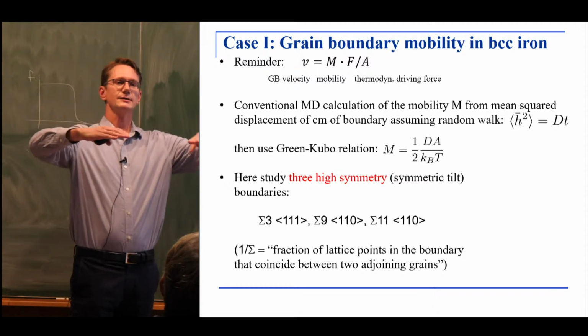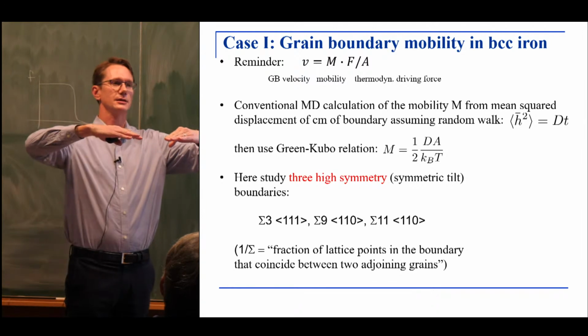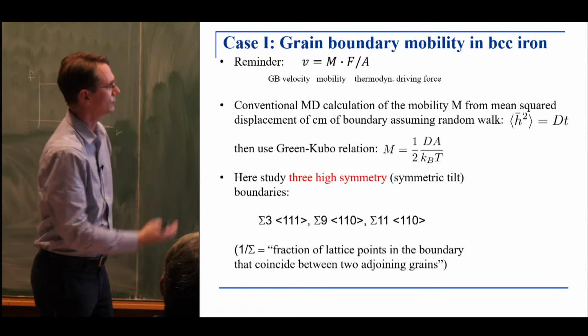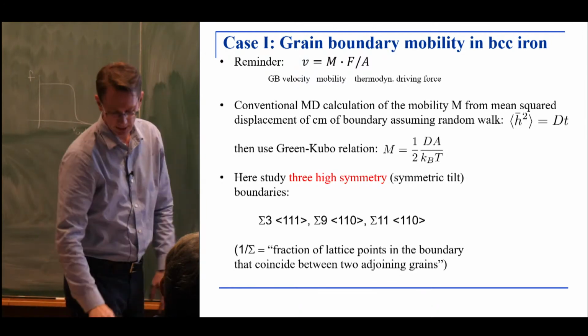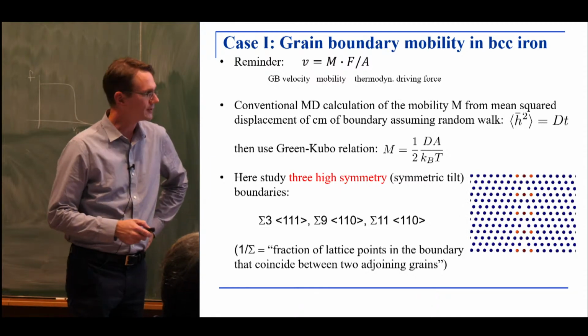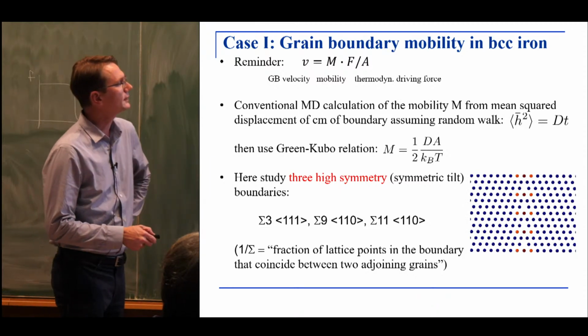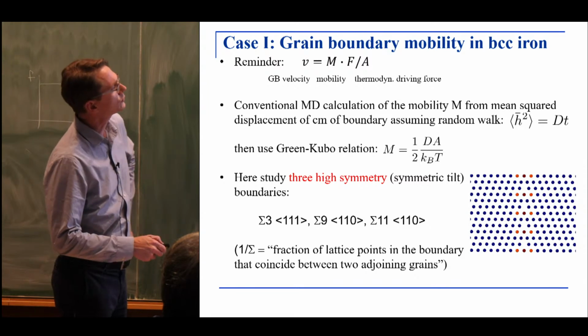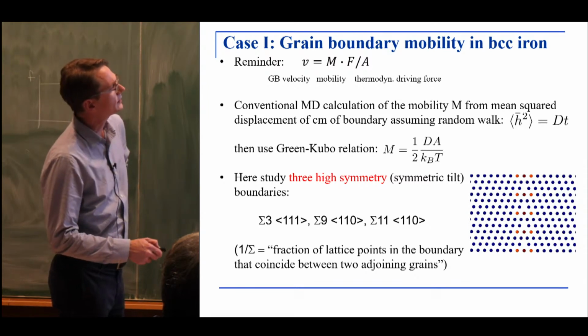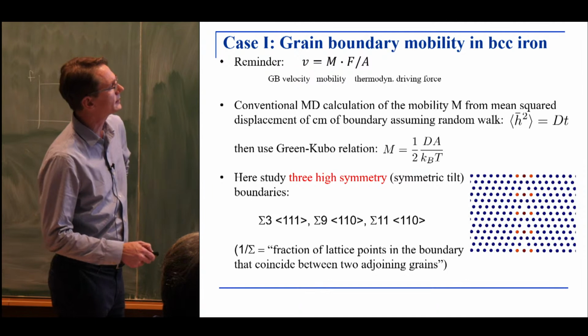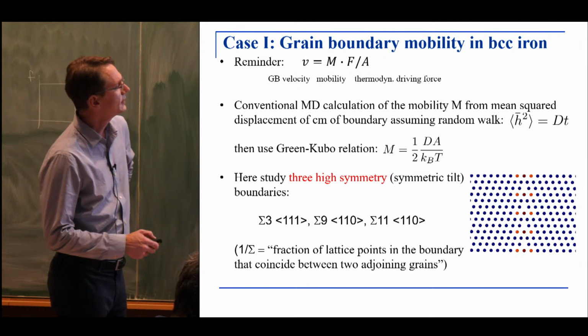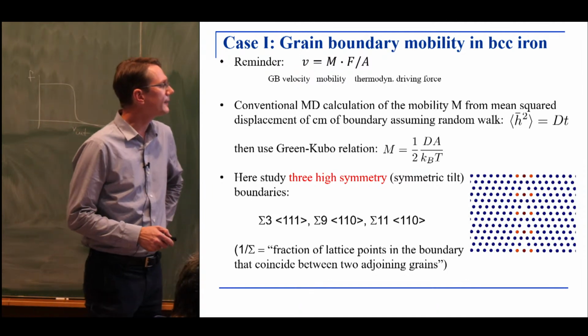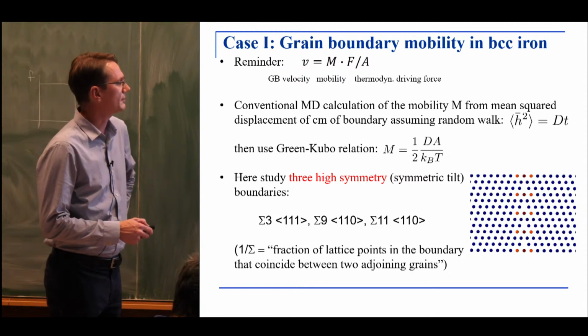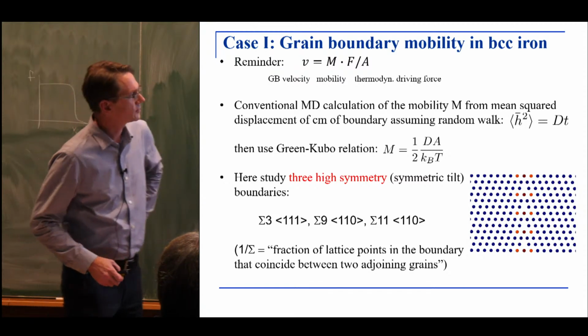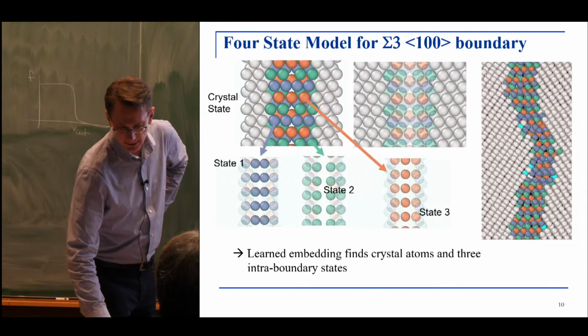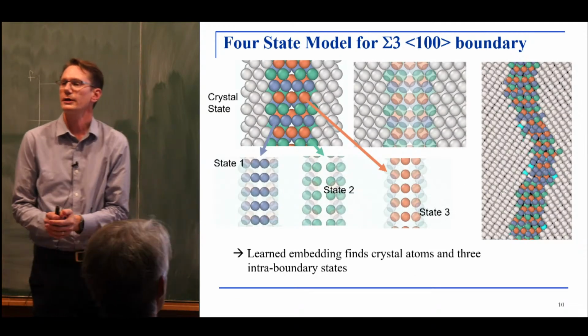You take two grains and rotate one against another along a crystallographic axis, in this case the 111 axis, by a certain angle. This is a picture of this sigma 3, 111 boundary. You can see there are two grains that meet at an angle, and you see the interface where the grain boundary occurs. This is a highly symmetric boundary, and the degree of symmetry is described by this sigma parameter. So we're going to look at that, and let's see what our Markov model can predict for this.